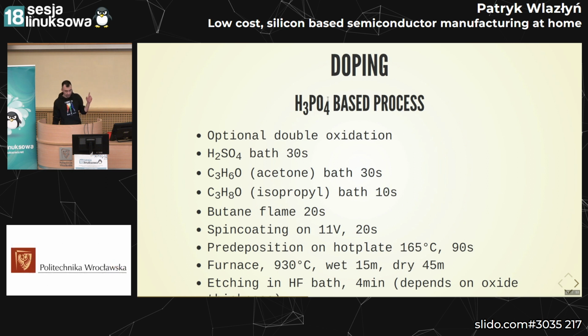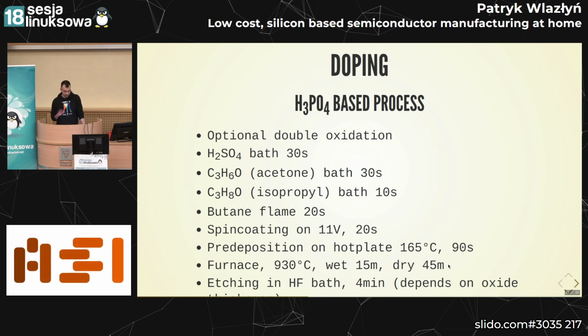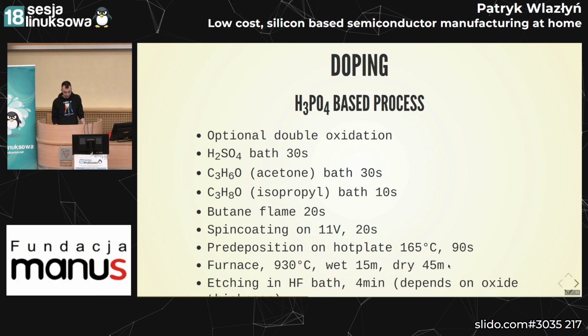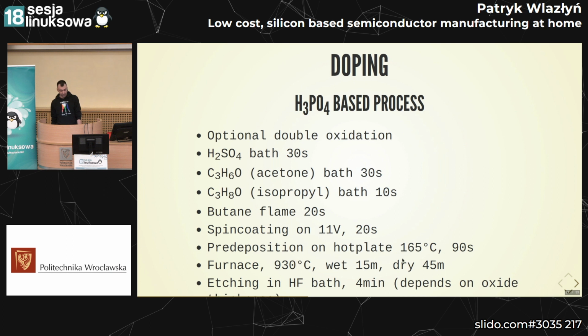And then when we have this phosphoric acid based layer on top, we can put it in a furnace at 930 degrees C. First we put it in for 15 minutes with pumped water, and then 45 minutes doing it dry. Maybe we'll have some more time to talk about why we do it this way, but let's leave it for now. And then we etch it in the HF for 4 minutes, depending on the oxide thickness. The bigger the thickness, the longer you have to do the bath, but HF will eventually etch all the oxide.